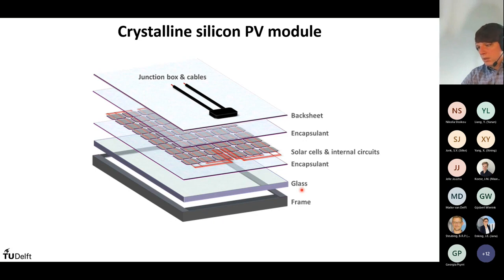And it's not regular glass for PV. We need a very transparent glass. It's even more transparent than window glass. So we need low iron amounts because iron causes absorption. If you see old glass, it's sometimes a little bit greenish, and then you have lots of iron. So we need about 10 or 20 parts per million of iron ions in our glass, which is the current standard for PV.